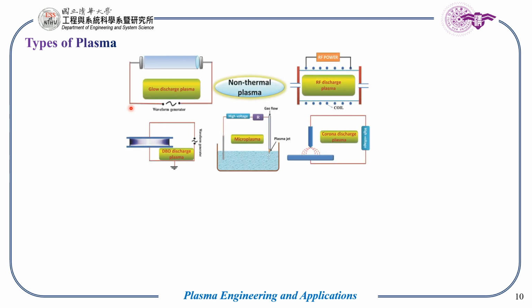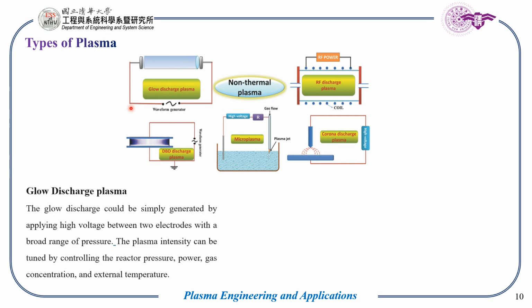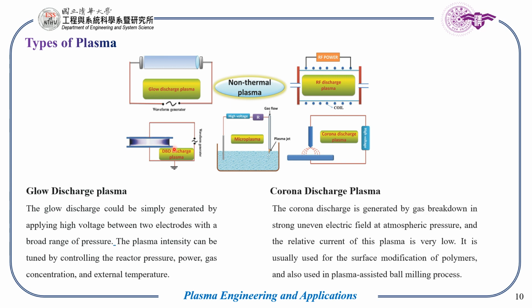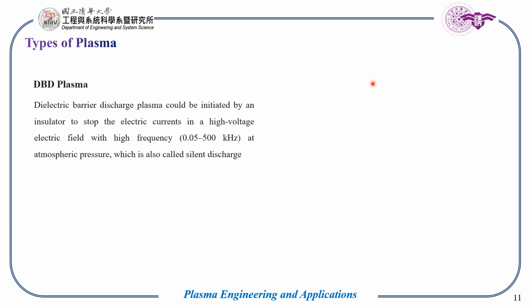And these non-thermal ways to generate the plasma can be further classified into glow discharge plasma, RF discharge plasma, that is radio frequency discharge plasma, corona discharge plasma, and DBD plasma. Coming first to the glow discharge plasma, it could be simply generated by applying high voltage between two electrodes with a broad range of pressure. The corona discharge plasma can be generated by gas breakdown in a strong uneven electric field at atmospheric pressure, and the relative current of this plasma should be very low. DBD plasma, dielectric barrier discharge plasma, could be initiated by an insulator to stop the electric current in a high voltage electric field with high frequency at atmospheric pressure, and it is also called a silent discharge plasma.